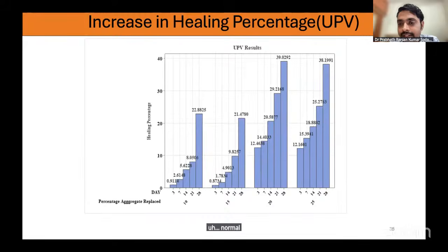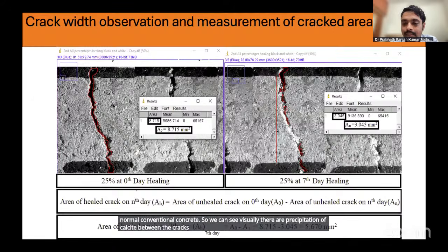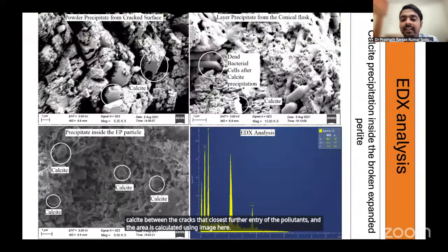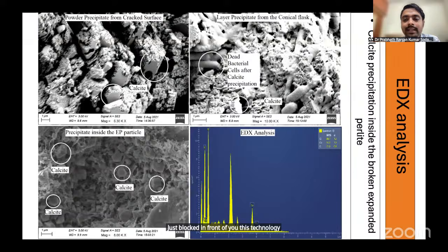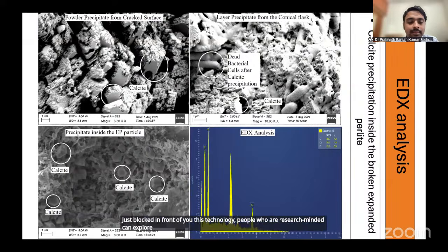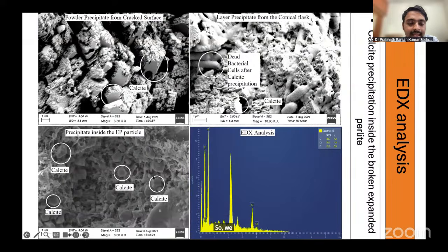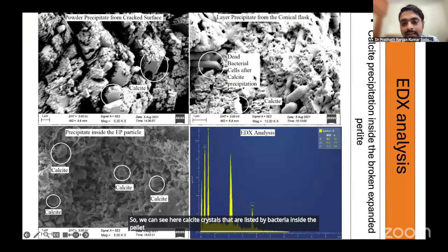normal conventional concretes. So we can see visually there is precipitation of calcite between the cracks that blocks further entry of pollutants, and the area is calculated using ImageJ here. I just brought this technology in front of you. People who are research minded can explore this in depth. So we can see here calcite crystals precipitated by bacteria inside the pellet after cracking. These were analyzed using EDX analysis, and we found a huge amount of calcite. It's pure calcite.